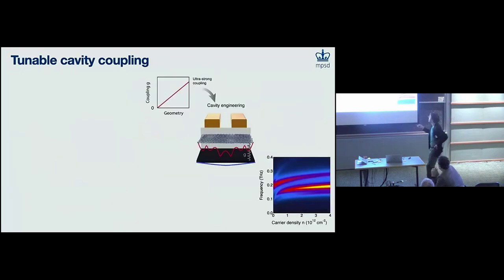If you have a waveguide geometry like this, in this device, this is 3 microns, this is also 3 microns, and that's 3 microns, maybe a couple microns here and here. What this does is the gold provides a patterned dielectric. It gives you an inhomogeneous screening environment for the plasmons. And long story short, this gives you momentum scattering pathways that turn on coupling between these modes and the two layers of different momenta. And that's how you get this ultra-strong coupling.